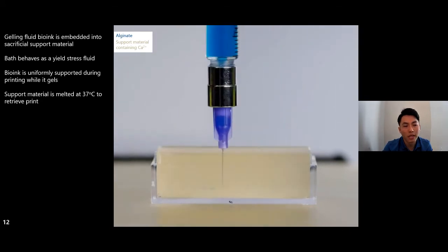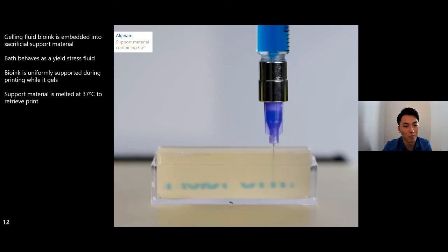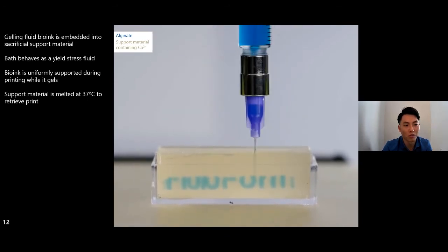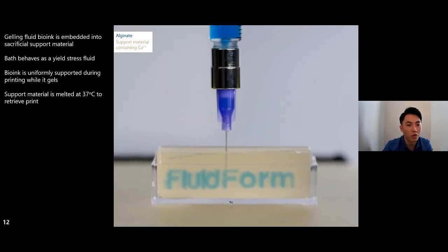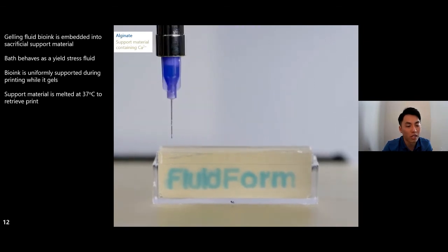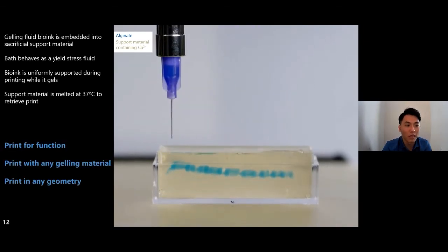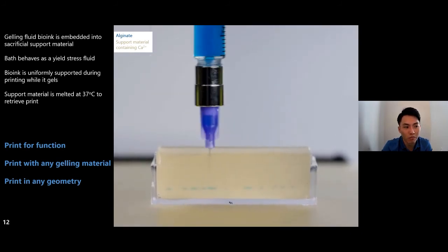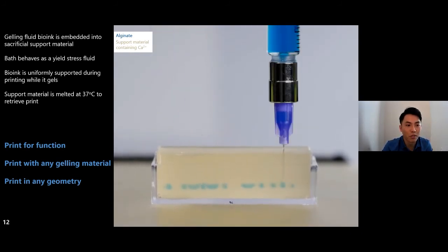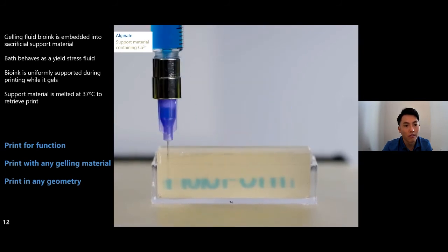And by the time we're done printing, we can actually melt away our support material because it's made of gelatin. It will melt at 37 degrees Celsius. And we can then retrieve our completed fully cross-linked print. And so this is what allows us to really think about printing with any gelling material, print in any geometry that we want to, and start to print for function.